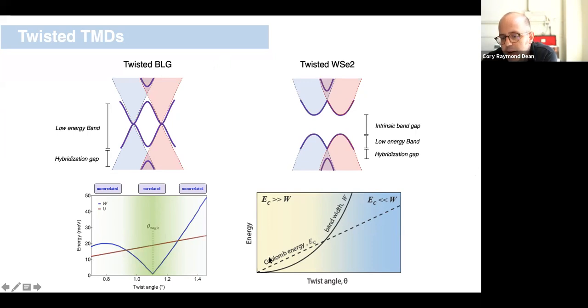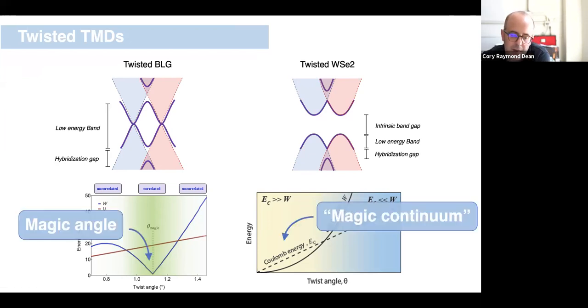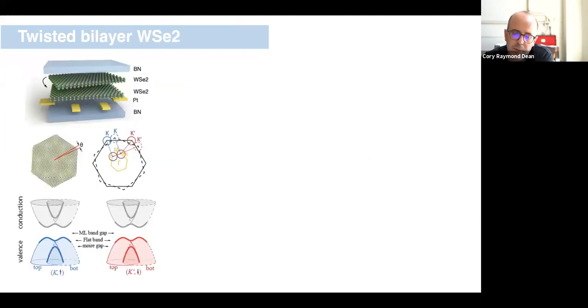And in twisted homobilayers, what I'm trying to argue is that there's actually a continuum of twist angles, not a precisely defined angle, over which you might expect the Coulomb energy exceeds the bandwidth. So we, tongue-in-cheek, identify this as the possibility of realizing a magic continuum in the homobilayer TMDs. Indeed, if you had a superlattice potential applied to any semiconductor and the wavelength were appropriate, you might imagine that you could access this kind of situation where you get a strongly correlated flat band. Okay, so that's the cartoon idea.